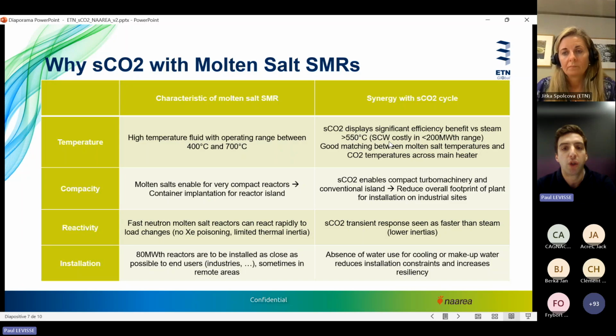And we could go for supercritical water, but supercritical steam has such a high cost in terms of thicknesses that it makes more sense on larger plants rather than plants of this size. And there's also a good match between the temperatures of the molten salt and the CO2 temperatures across the main heater. That's more for the thermodynamics of the cycle, but 400 and 700 is really a good match for sCO2.